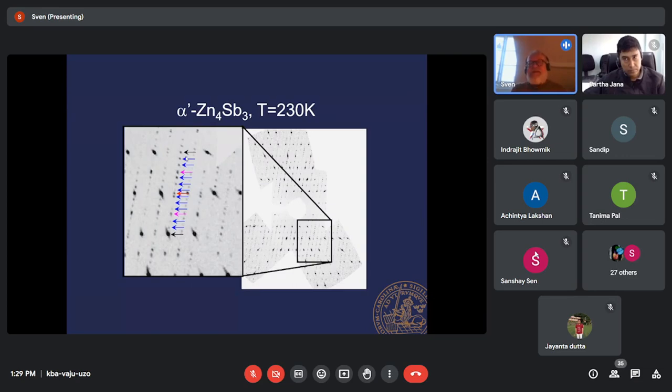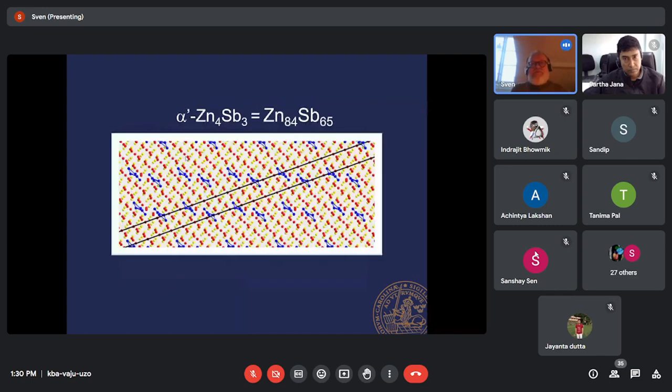Again, this is triclinic. There are 6 individuals of it. It coexists with the fourfold, which there are also 6 individuals of. The twinning becomes horrendously complex, but it is possible to solve the structure. It looks extremely similar to what we saw before.